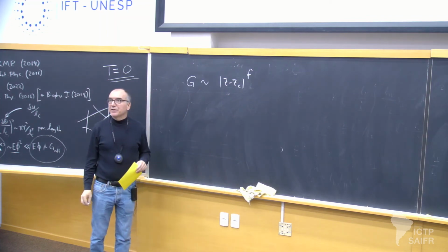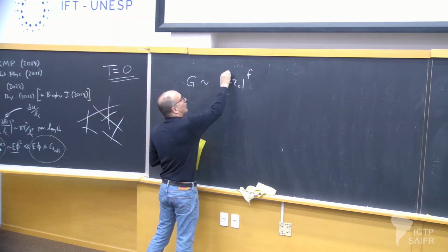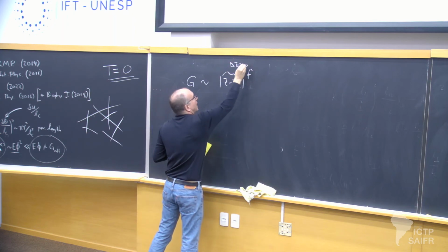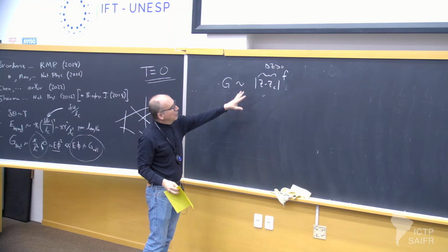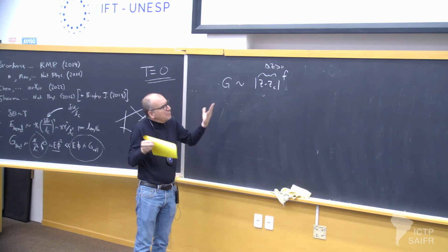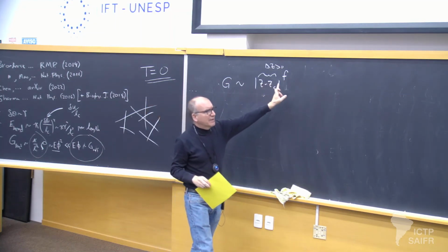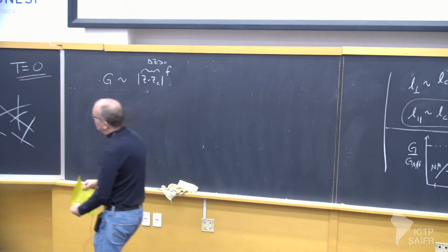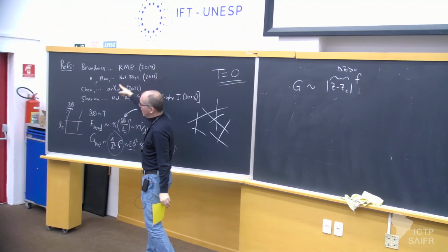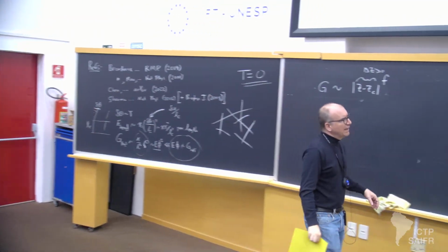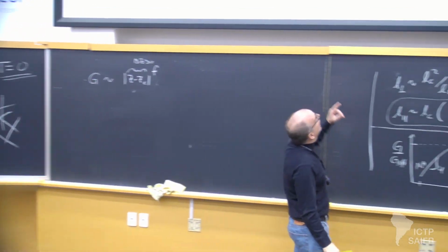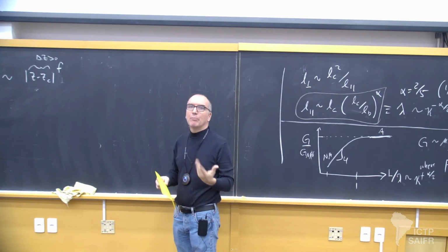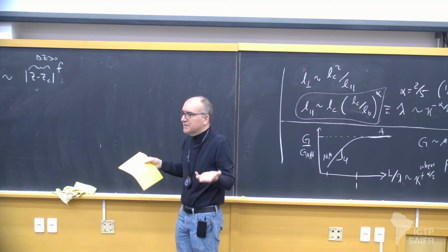So basically it's saying that there's some power law of what I'll call delta Z when it's positive, which looks like that. Okay, that's just a postulate. If you measure that f exponent, a mean field model that Tom and Jiaming worked out gives 1. The simulations show a value definitely different from 1, like 1.4. So it's non-mean field. That's interesting.